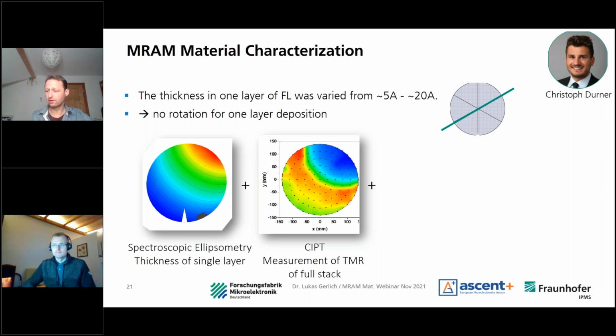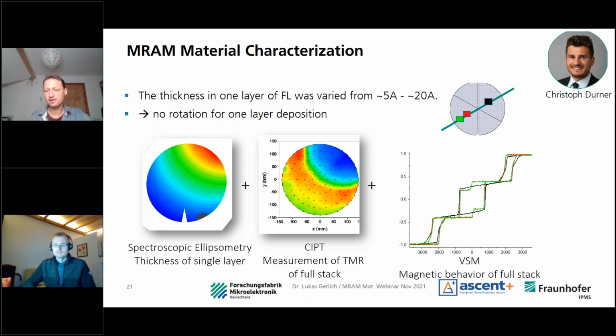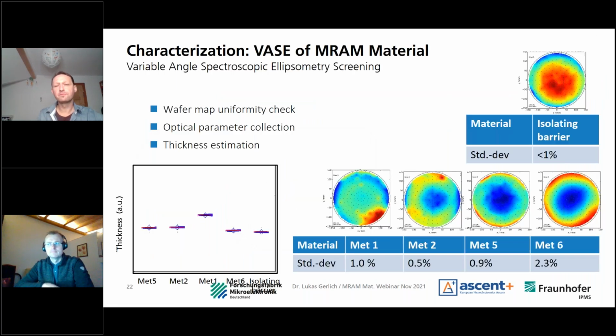And this can also be seen in the current in-plane tunneling measurement for the tunnel magnetoresistance in a full stack, and also the magnetic behavior in a VSM, a vibrating sample magnetometer, is possible to see if you have samples from thicker layer and lower layer within the stack. Of course, the wafer map in ellipsometry is quite good.